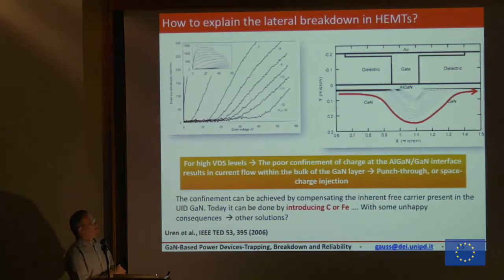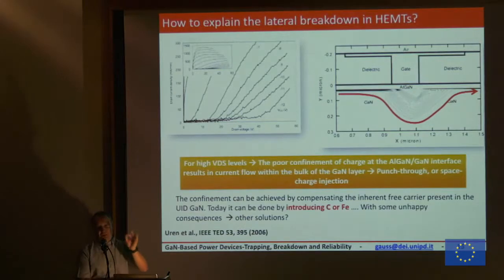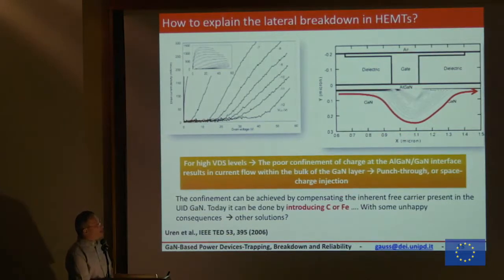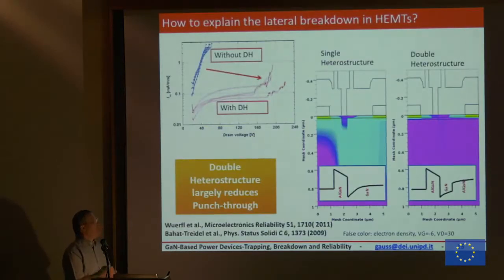So again, there is no way to make my layers without these guys, carbon or iron, in order to compensate and make this layer insulating. This is fundamentally important for power devices, because I have very large voltages here, 600 to 1000 volts, and at these voltages, this punch-through will be there. If I want to remove that, I have to compensate. And this is a very critical point that is taking a lot of effort for all the companies to solve this problem. Another possibility to avoid the punch-through is making a double heterojunction.